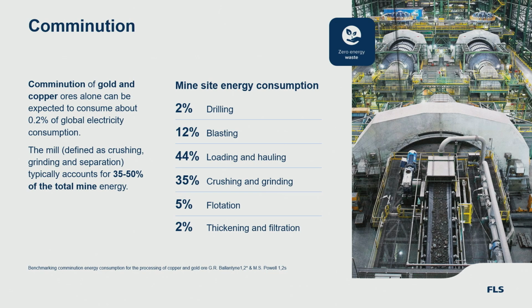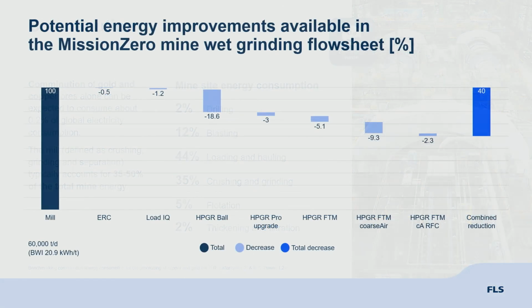So we took some data on copper and gold mills from Ballantyne and Powell from the SEEK initiative in Australia, and we looked at where the energy was being used in the mine sites. And 0.2% of global energy is used in crushing and grinding for gold and copper ores. That's a significant amount. And when you take into account the amount of more copper that we've got to produce, I haven't worked it out. Maybe somebody could calculate that for me. That is a significant amount of energy that we need. So we need to reduce the energy used in crushing and grinding.